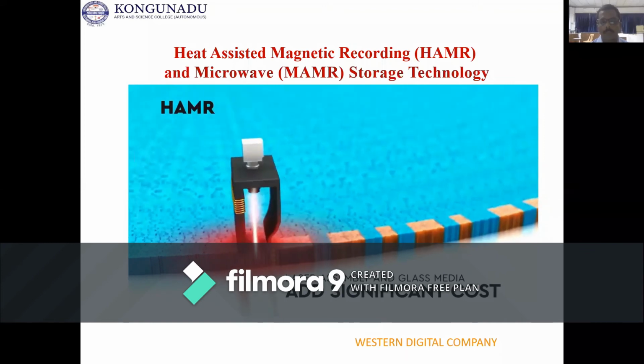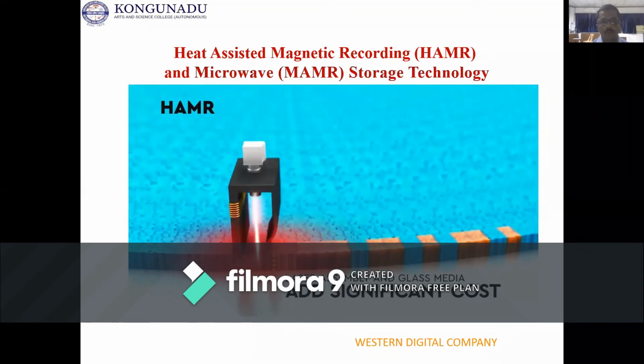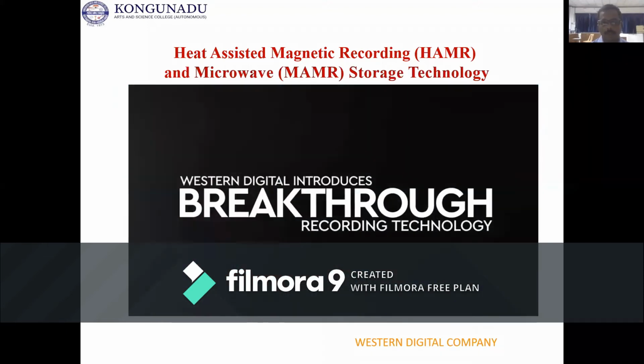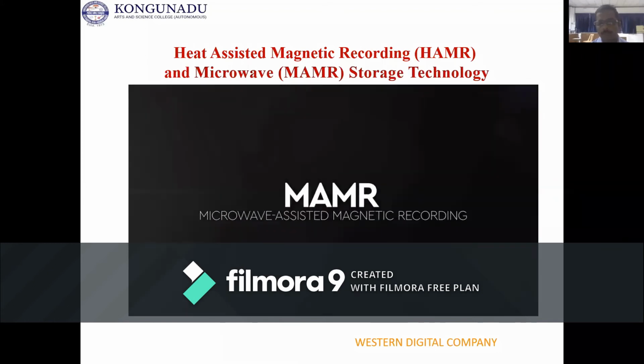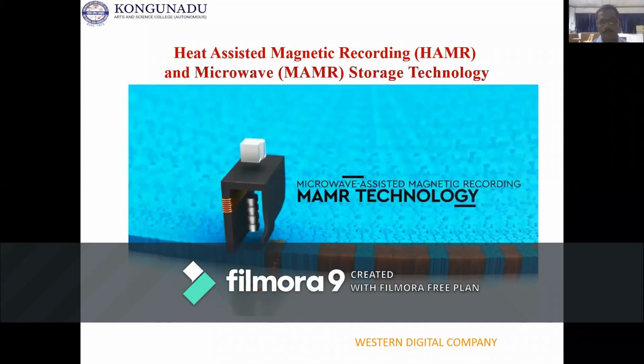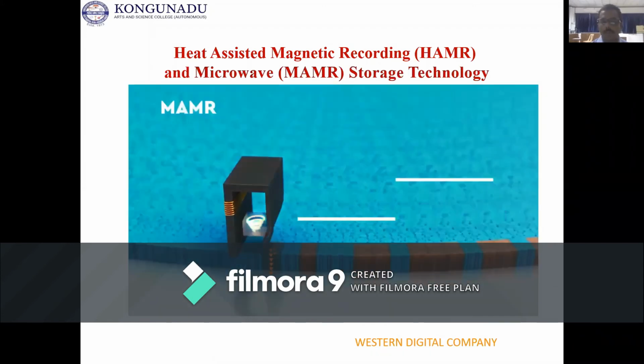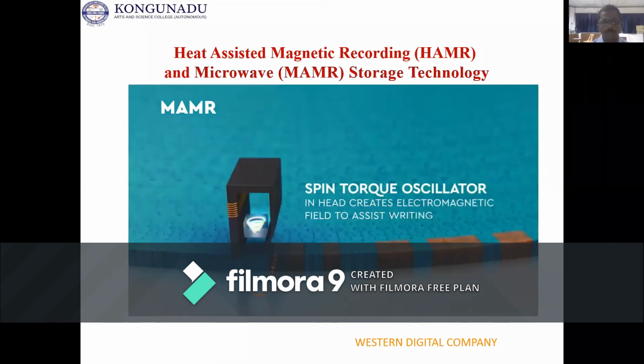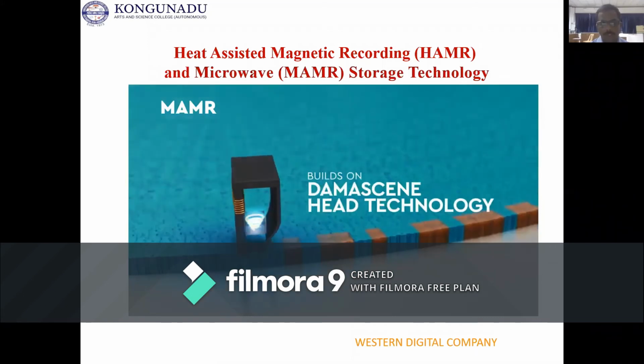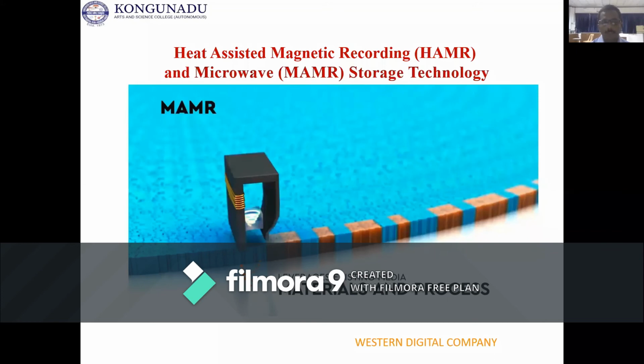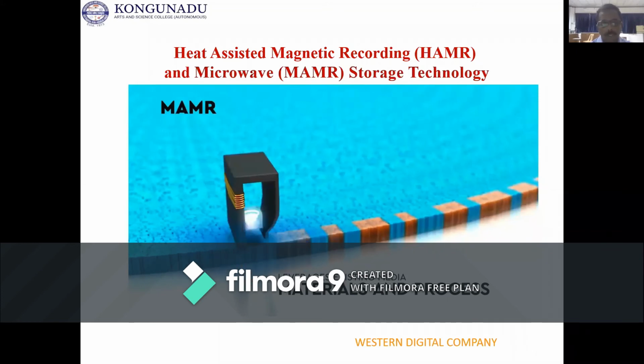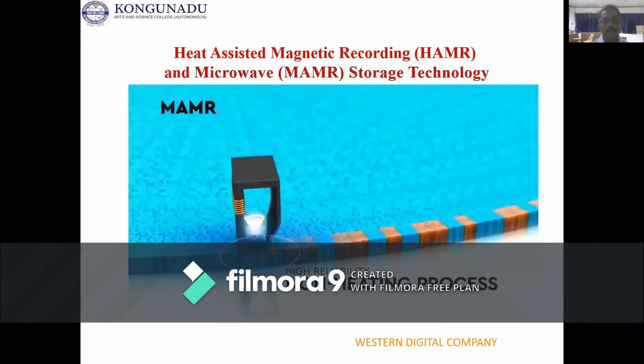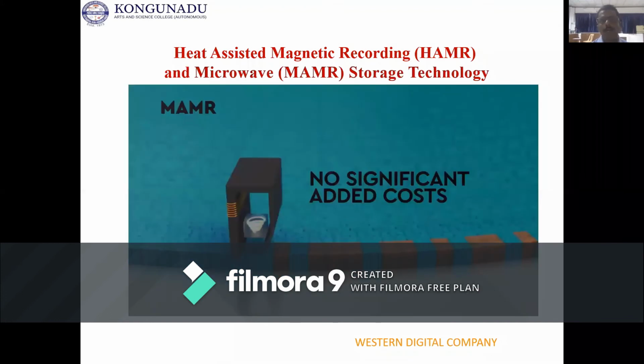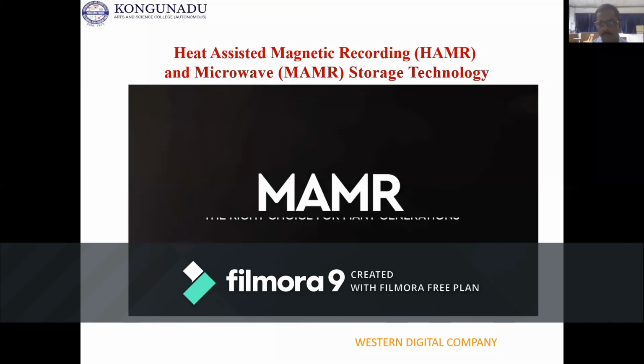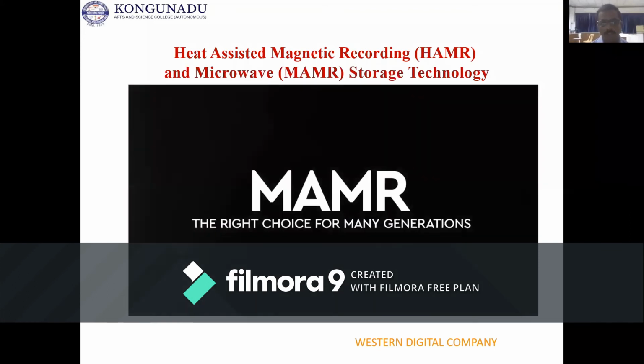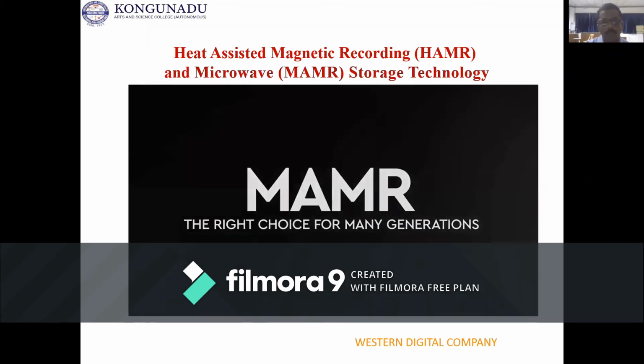In heat assisted magnetic recording, we use a laser which can harm the magnetic layer and disturb the storage devices. So this Western Digital company came up with a new idea, a microwave device using a spin torque oscillator, which uses a low temperature and megahertz or gigahertz frequency energy, and it stores the magnetic spin without disturbing or harming the layer on the surface of the magnetic hard devices. So this technology is going to come to the market in the near future, having 40 terabytes per inch square. So you can have a hard disk of 40 terabytes in your normal computer itself around 2023 or 2025.